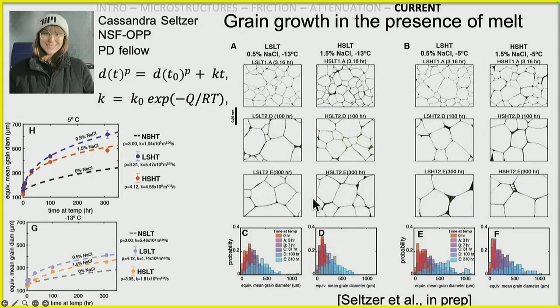And so it was nice for the undergrads to have a tactile visual response. And she was able to take those values and plug them into the standard known grain growth law and determine these values, P and K. And I'll just cut to the chase. Here the bottom curves are the pure ice samples.